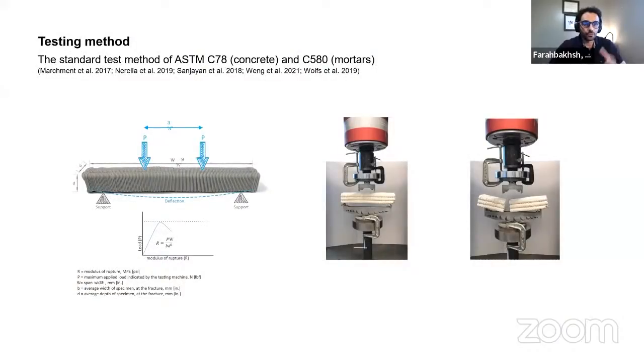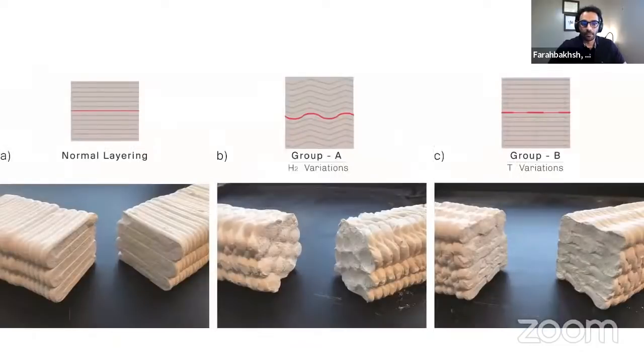And through a series of physical ASTM tests, we found the flexural strengths of the specimens. You can see on the left side, it's the conventional layering, and in the middle, you can see the difference, how much difference it makes when you change the parameters and the bond strengths between layers.